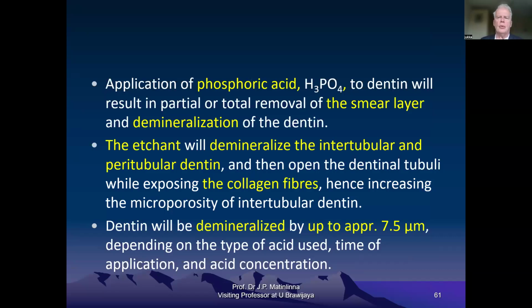Application of phosphoric acid to dentin will result in partial or total removal of the smear layer and demineralization of dentin. The etchant will demineralize the intertubular and peritubular dentin and then open the dentinal tubuli while exposing the collagen fibers, hence increasing the microporosity of intertubular dentin. Dentin will be demineralized by up to around 7.5 micrometers, depending on the type of acid used, time of application, and acid concentration. These are important parameters.